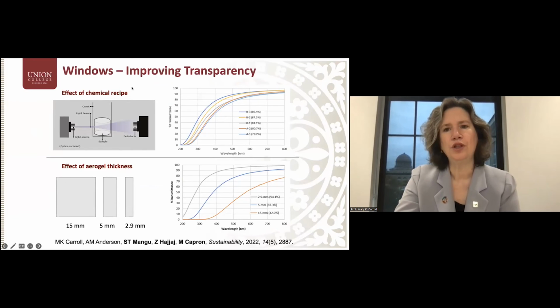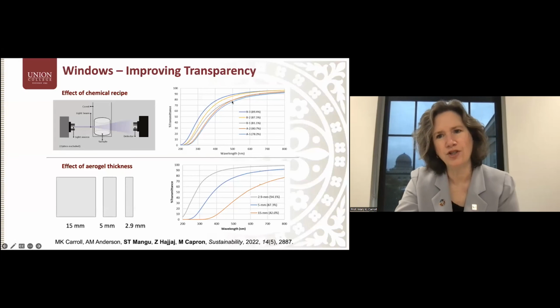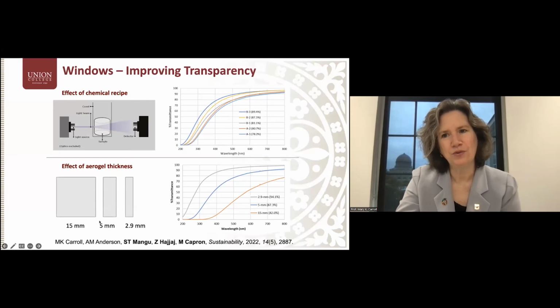We've done work with looking at the effect of the chemical precursor recipe on the transparency of the resulting material. And here we're looking at percent transmittance as a function of wavelength. And we can see that by modifying the recipe that we use, still using the same starting materials, but changing the ratio, changing the amount of catalyst, we're able to get to more and more transparent. And something that will not be a real surprise to anyone, if we go to thinner aerogels, even with the same recipe, because the path length is shorter, the amount of scattering that occurs would be less, and the translucency can go up.